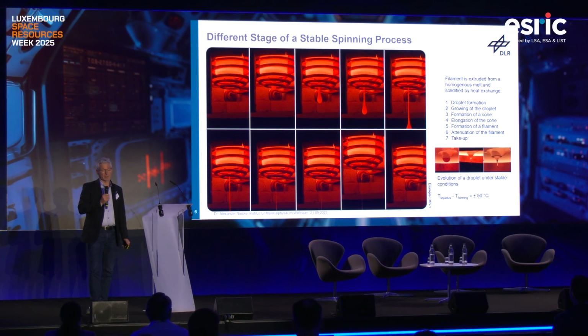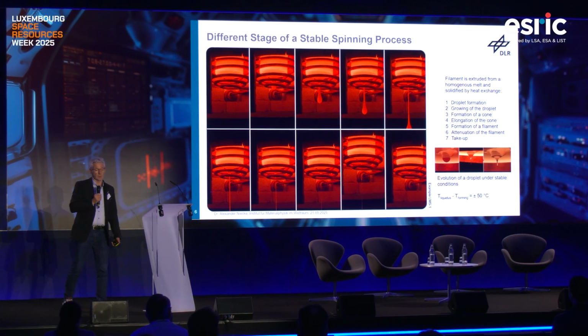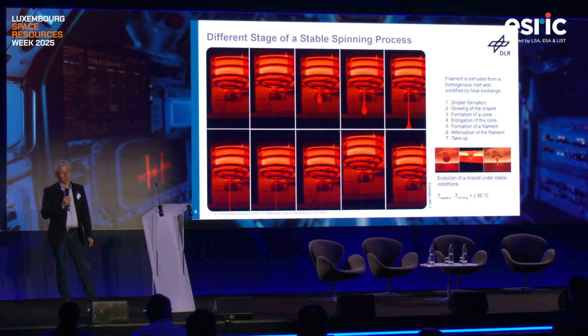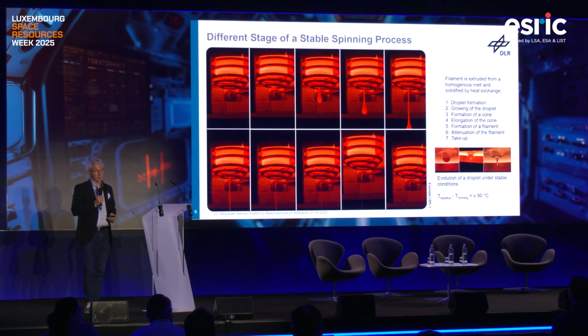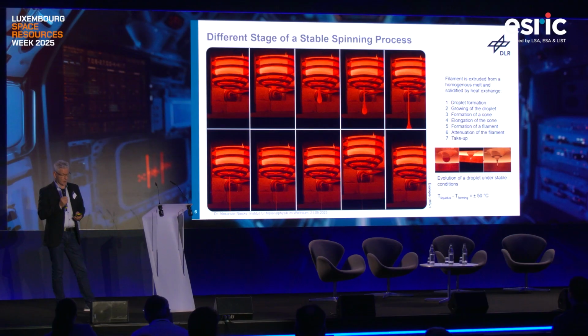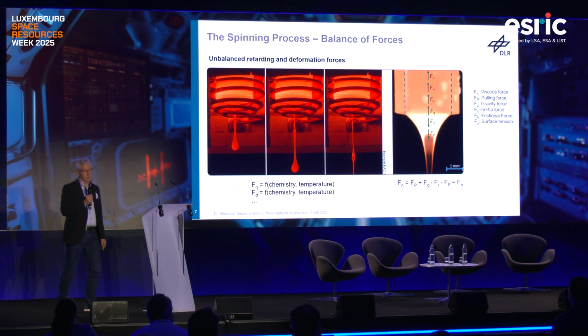To assess if this system is really working, there is a simple formula to calculate the forming gap or the temperature range in which this process might be stable. That means you have to determine the forming temperature based on the viscosity, depending on the chemistry, and the liquidus temperature. And this forming gap should be more or less 50 degrees C. The higher, the better, but 50 degrees C is already a good temperature.